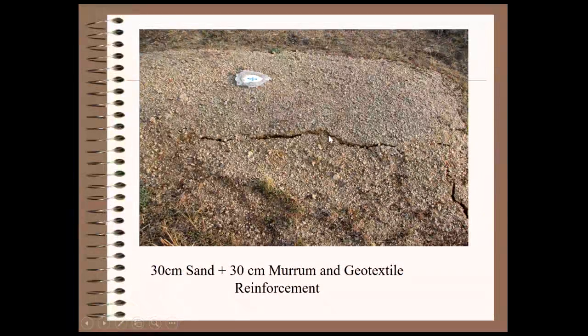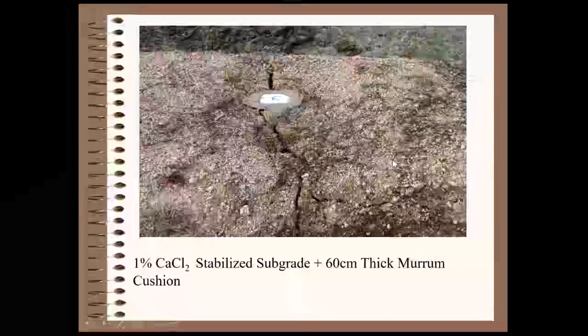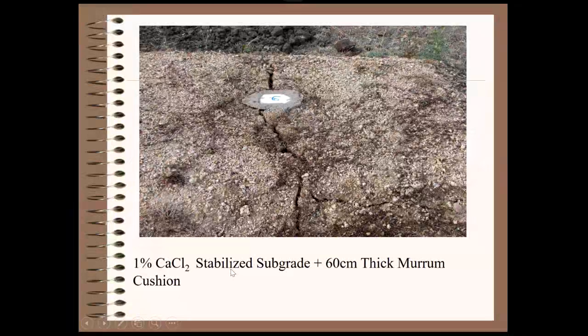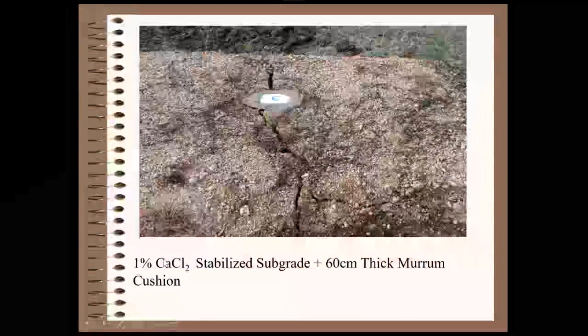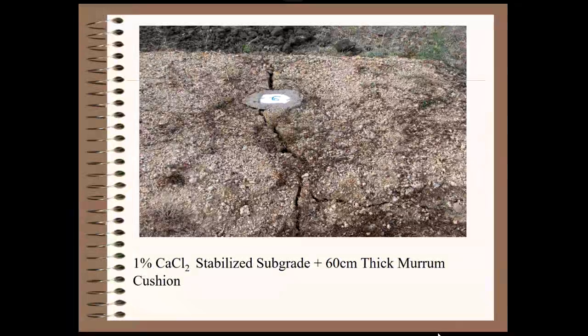That is why only slow and steady. That concept is true even with black cotton soils. Somehow we have to manage our drainage systems so that water ultimately enters, but let it enter slowly, by which there is a mechanism actually, cohesive bonds will be developed within the clay to self-stabilize the system, so that it will come to self-stability with little volume change. That is our only success. And ultimately here, even when 1% calcium chloride stabilized and then murrum cushion is used, that is also cracked. That means whatever it is, calcium chloride, lime, cement, etc. may be good for swelling control, but against shrinkage, they are helpless.